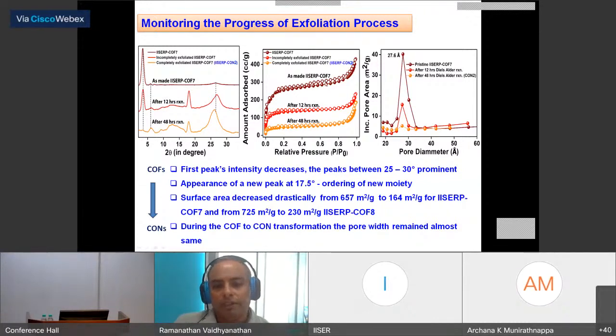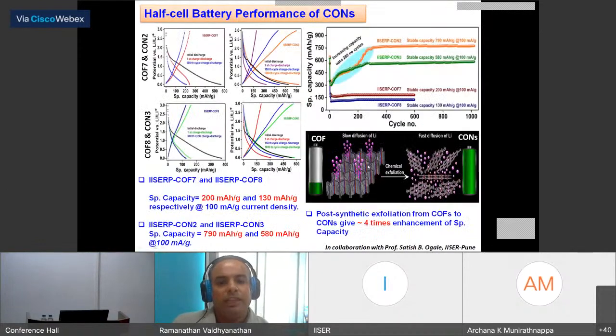And also you can follow it from the fact that the porosity systematically drops as the reaction is continued. But the important thing is the pore volume does not change, which is something you would expect, because the pore size of the COF, whether you are in exfoliated form or in the COF form, will have to be the same because they are both polymeric and the pore size remains the same. And then we are excited by what we have now, and we wanted to see if the exfoliated form of the COF has any advantageous impact on its anodic characteristics as an anode in a lithium-ion battery.